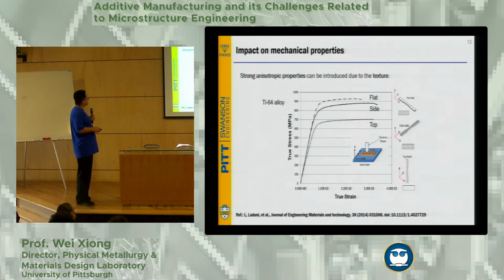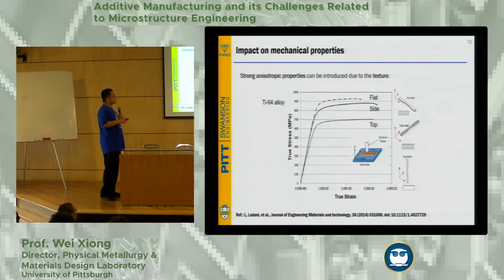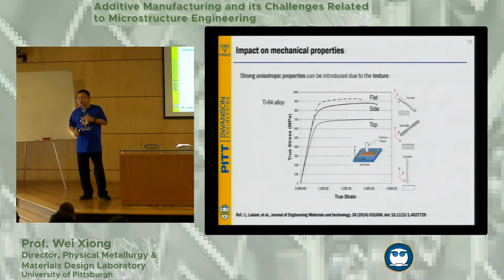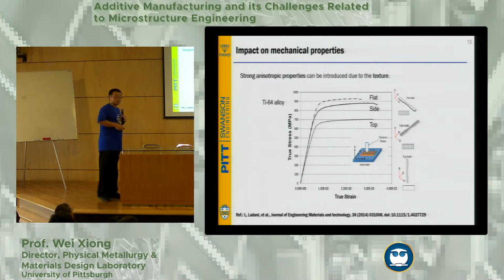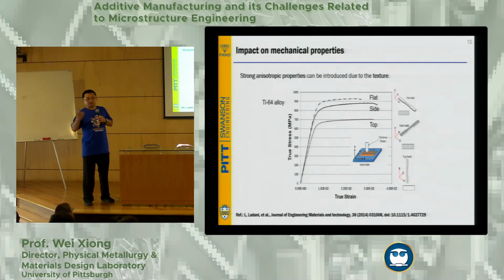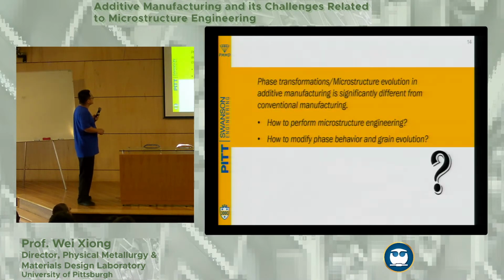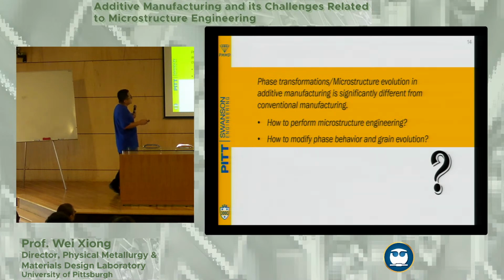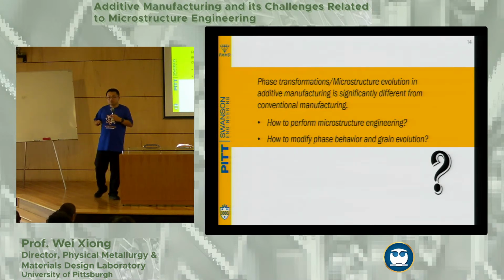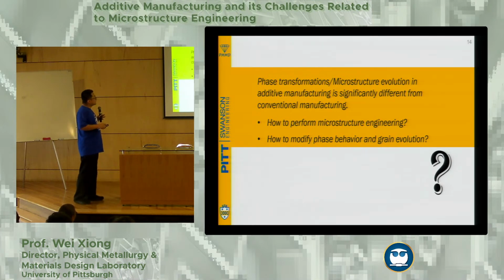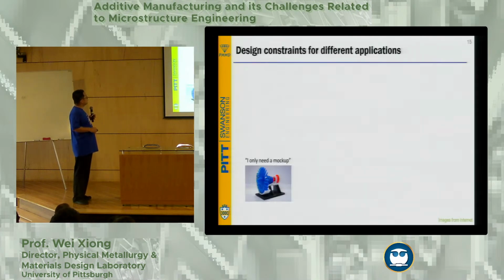So what is the consequence if you have such a heterogeneous microstructure developed with the texture? If you don't design this well, if you don't introduce some good heat treatment to tailor the structure, then you can see some of the structures will introduce very strong anisotropic properties in the tensile strengths. And of course, you can test more, with magnetic properties and so on, all right? So, here is a question, right? You have phase transformations and microstructure evolution. I think these two are almost identical concepts. Then they're significantly different from the conventional manufacturing process. So how do we perform microstructure engineering, how do we modify phase behavior and grain structure? That's a kind of challenge, all right?